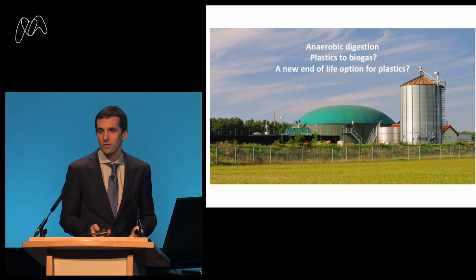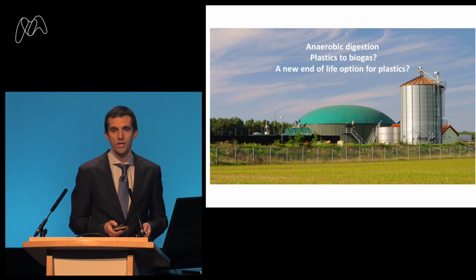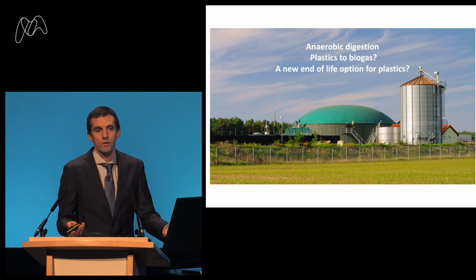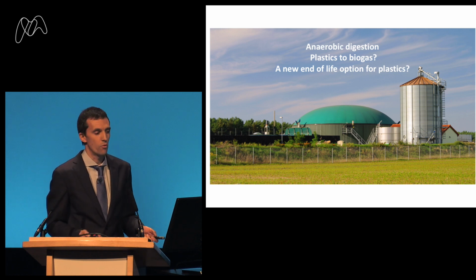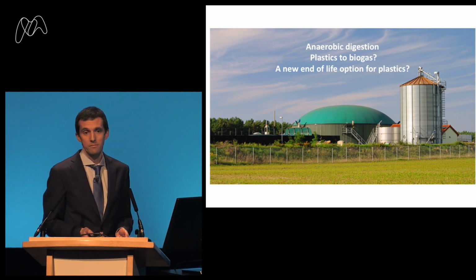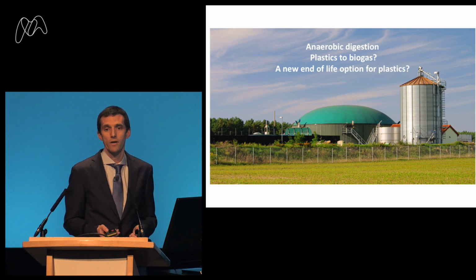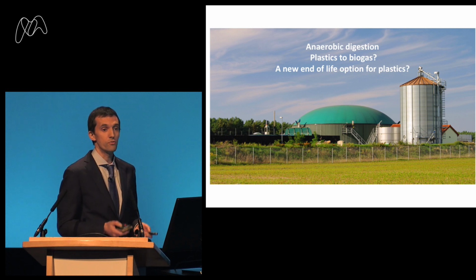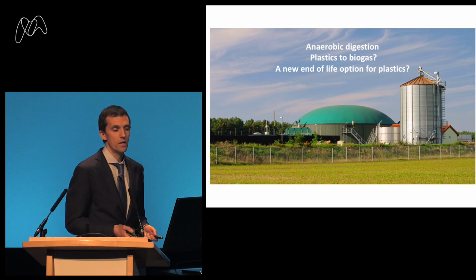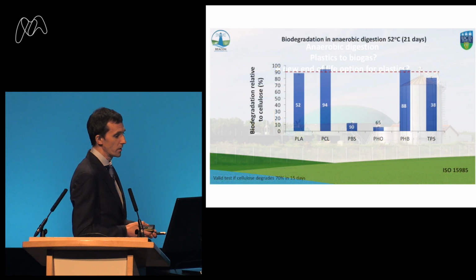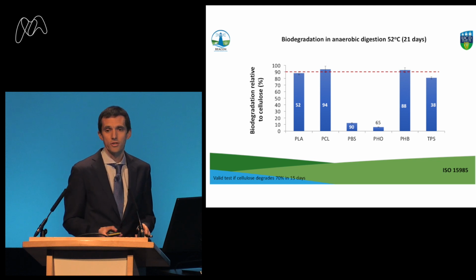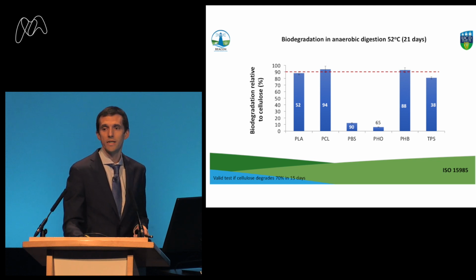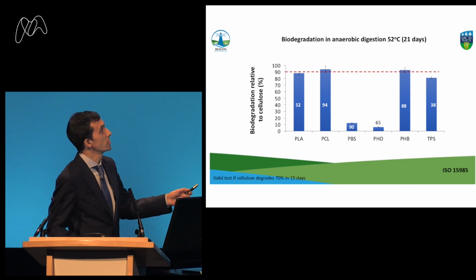And what about anaerobic digestion? If I was to say to you, let's anaerobically digest plastic, you'd say that's madness, that can't work. Polyethylene, polyethylene terephthalate, polystyrene, that won't work. But with biodegradable plastics, you have an opportunity. So you're offering a new end of life opportunity for plastics if you substitute petrochemical non-degradables with degradables. Anaerobic digestion requires 52 degrees centigrade and 21 days of incubation in order to meet the international standard. PLA just falls short of the 90% degradation.